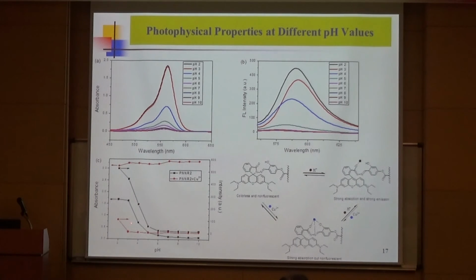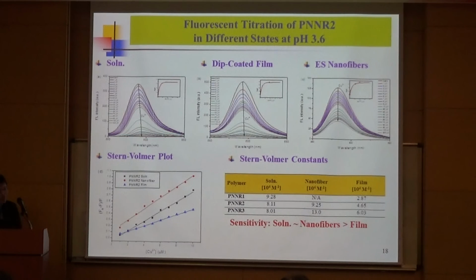Okay, so in order to get a clear on-off ratio between before and after addition of copper ion, we chose a pH value around 3.6 to further study the fluorescence titration behavior. Here again, we study the fluorescence titration behavior of PNNR2 copolymer in 3 different states: dilute solution, dip-coated thin film, and the electrospun nanofiber. A similar fluorescence response was observed among these 3 different states. With increasing copper ion concentration, we can see the fluorescence quenching with very little spectral shift.